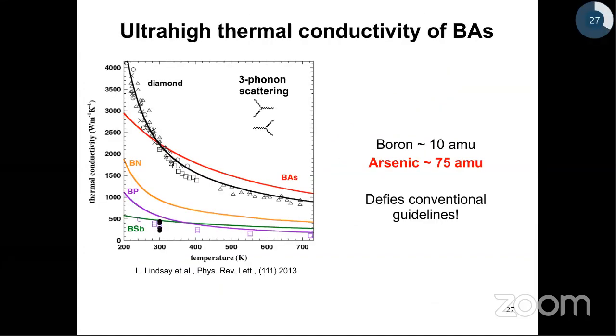But as a surprise, in 2013, when Lindsay and co-workers did the calculations for several materials, they found, using this conventional approach, that is with three-phonon theory, that the thermal conductivity of boron arsenide can actually exceed that of diamond beyond room temperature. Notice that boron arsenide has almost 3 times higher average mass than that of diamond. So it is a heavier material than diamond, therefore defying the conventional guidelines that I presented earlier in the previous slide. Yet their calculations using three-phonon theory, that is the conventional theory, predicted that the thermal conductivity could be higher than that of diamond.